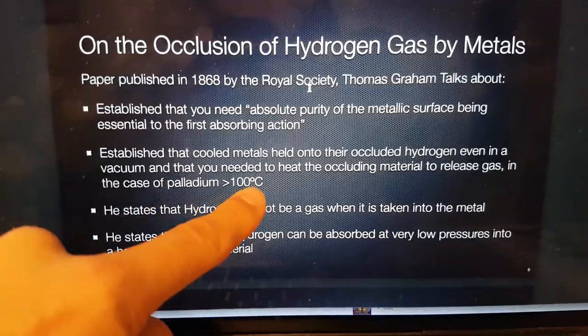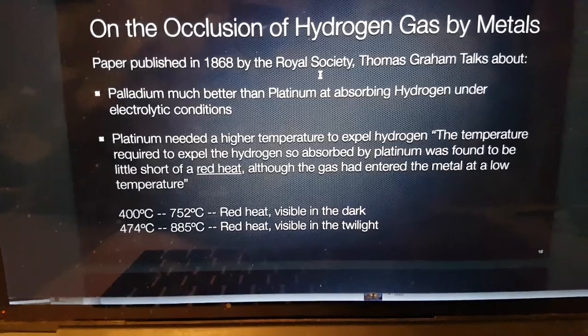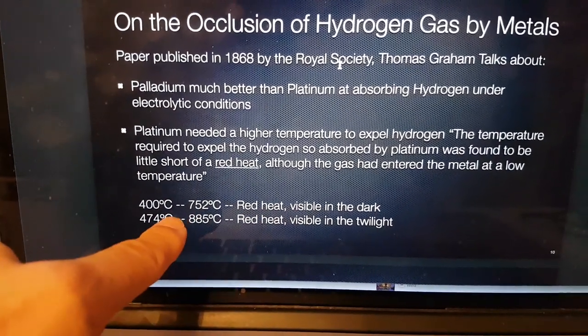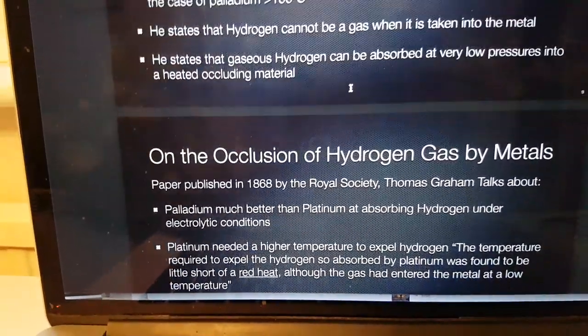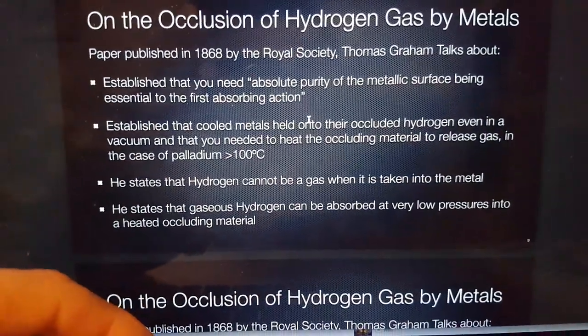And so here it's saying, established that the cooled metals held onto their occluded hydrogen, even in a vacuum, and that you needed to heat the occluding material to release the gas, in the case of palladium, 100 degrees C. And I think he found in the case of platinum, you needed to be at red heat, which is, you know, at least 400 degrees C. So really everything you need to know is here right in this paper about how you should try and get the first absorbing action optimal